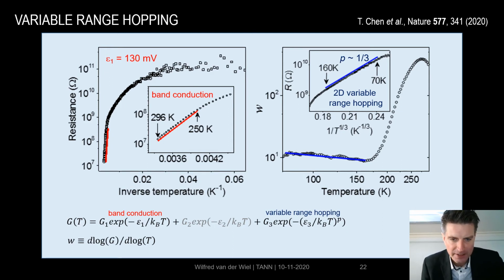This comes with these nonlinear IVs. From the exponent here in the expression for variable range hopping, we can derive that we basically are in a two-dimensional limit. So transport basically takes place in a plane close to the surface of our device. And the nice thing is that this happens basically up to around 100 to 150 Kelvin, so we can operate our devices at much higher temperature as compared to the ones that we used before with the gold nanoparticles that had to be operated at sub-Kelvin temperatures.